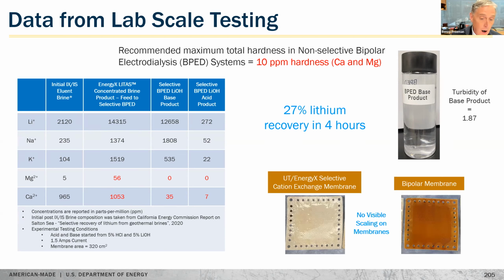This shows our selective cation exchange membrane and our bipolar membrane. The lithium hydroxide solution flows between these two membranes. If there were scaling, we would see it on these membranes, and we see no evidence of that. Next slide. And so far, we've seen that we can tolerate in the range of 1,000 to 1,500 ppm hardness, which we think is a game changer for the use of bipolar electrodialysis in this process.